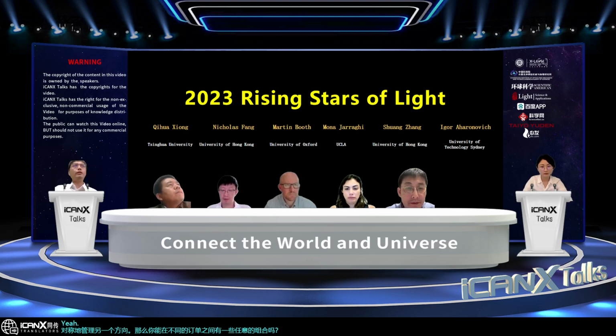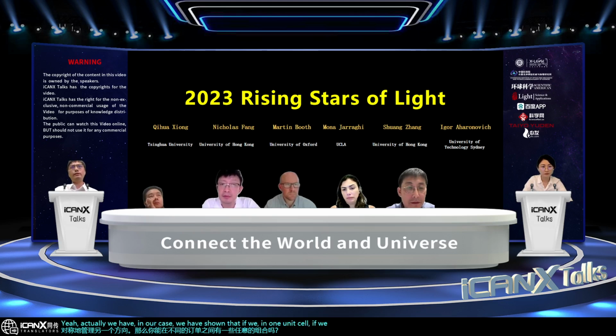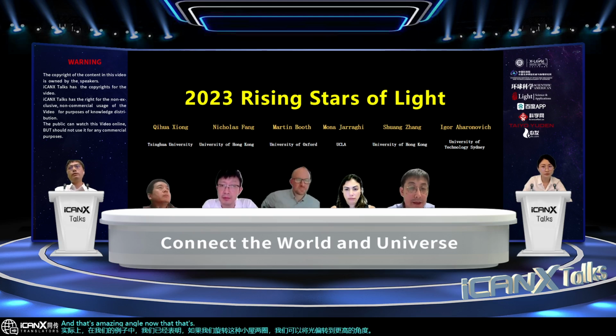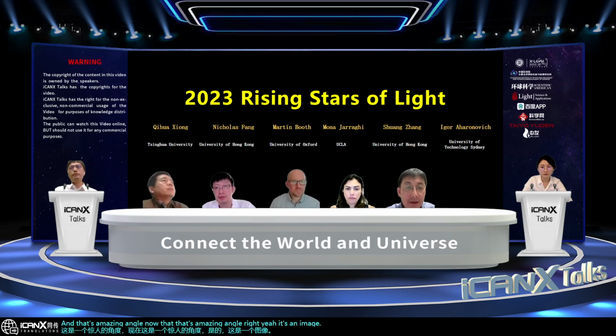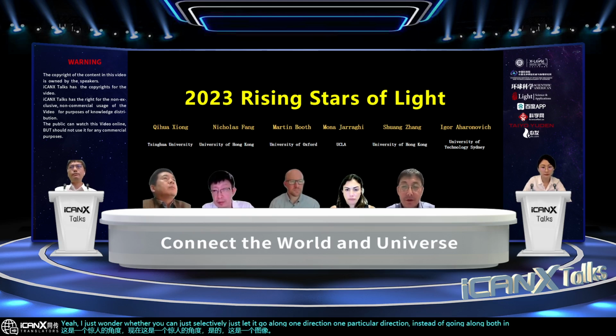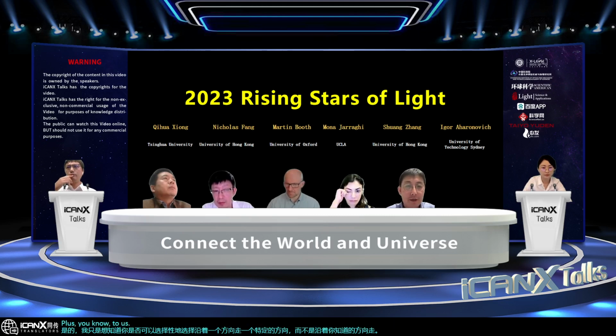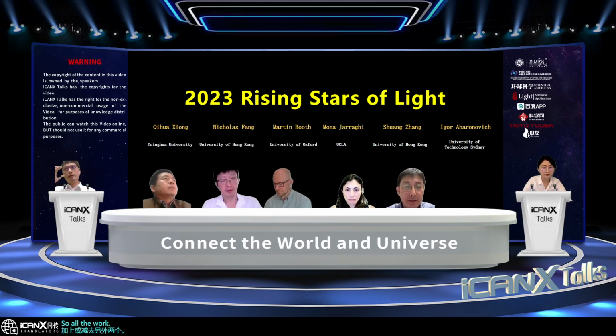Actually, in our case we have shown that if in one unit cell we rotate this kind of notch with 2 rounds, we can deflect the light into a higher angle. And that's a lasing angle, right? Yeah, it's an emission angle. I just wonder whether you can selectively let the light go along one particular direction, instead of going along both plus 2 or minus 2 orders, so all the light just goes in a single direction. Is that possible?